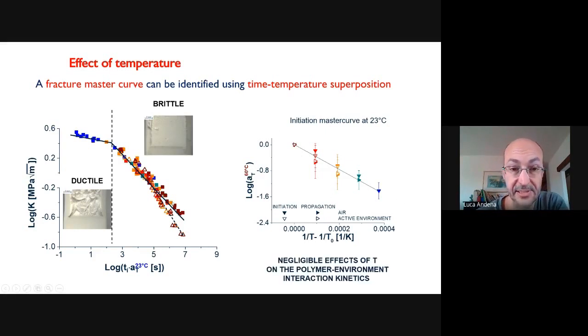This is an important result because it says a few things about ESC. It means that, at least in this case, since the shift factor is the same in air and the environment, the acceleration factor is only due to the material viscoelasticity and not to a change in the ESC process itself. And this is interesting because it means that you are free to change the temperature as you wish to accelerate testing. But not only that, you can take data from the test you perform at high temperature to rank the different materials, for example, at 60 degrees, and use those data to make predictions about the expected lifetime of products, which, for example, work at 23 degrees or not much different, like the bottles which are stored somewhere before being put on the shelves.